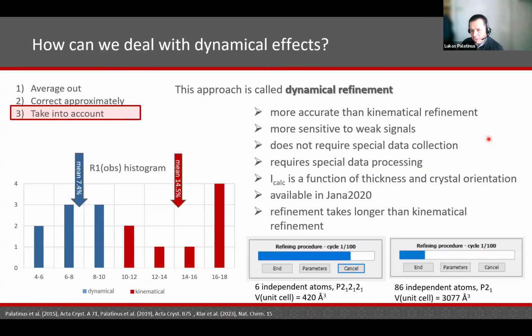The theory is here, so why not use the theory to calculate the expected diffracted intensities using dynamical refinement? It brings a number of advantages over kinematical refinement, so over the case of ignoring the dynamical effects. One of them that is shown here in this plot is improved fit, so better accuracy of the fit.